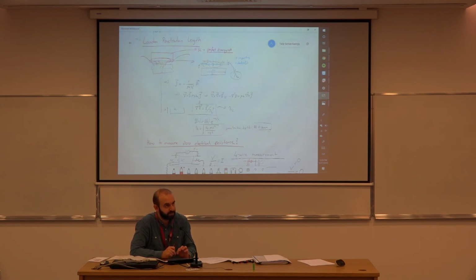Do these Cooper pairs located on the surface not act as a scattering point for other Cooper pairs that pass through? I'm thinking about something like a superfluid, so there are some parts that are bound. So, I don't know the answer. Perhaps that's similar to formation of vortices, as we'll see especially in type 2 superconductors. In the transition from normal conductor to superconductor, in that in-between regime, you first form vortices. But again, we are talking about only a very small depth of material, only a few nanometers thick skin on the surface.